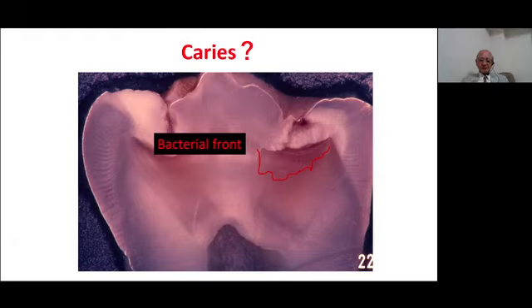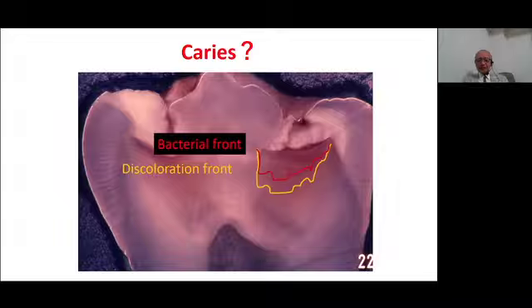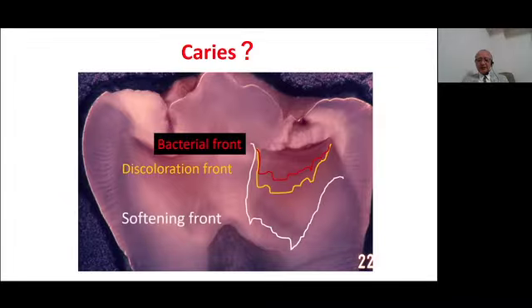The bacterial invasion front may be located like this. And if you apply the caries staining dye solution, it is located like this. It is a little bit deeper than the bacterial invasion front. However, the dentin softening front is located at a much deeper part, because the acid produced by bacteria can penetrate much deeper in dentin. That's why at the deeper part of dentin, this part is demineralized. Because of the demineralization and the reprecipitation of the mineral crystals, the transparent dentin is created.